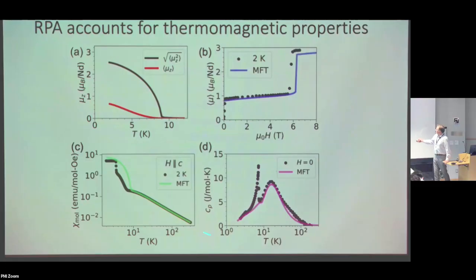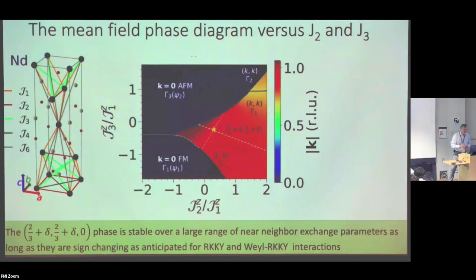This is the specific heat, for example. That's the Schottky anomaly, which is well accounted for. These peaks are critical phenomena that we shouldn't expect to account for, and so they don't. This is a magnetization curve. All of the critical fields are accounted for. This is the temperature dependence of the moment, which is well accounted for, as well as the susceptibility as a function of temperature. So all of these things work pretty well.